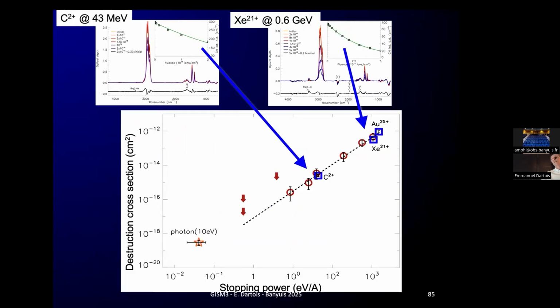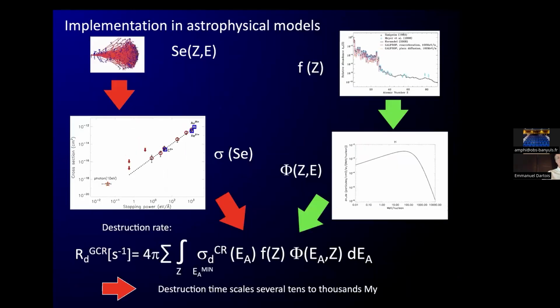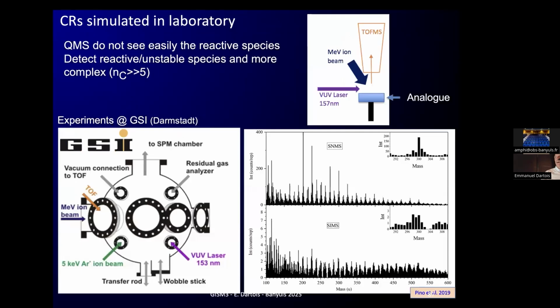You can see the destruction timescales, which is what we have in the hands-on, that we need to find the factor. And you can estimate the destruction rates, which are important to know if what you are seeing should be there or shouldn't be there, or do you need to reproduce these dust grains regularly, or are they resilient to the exposition of cosmic rays? And in some cases, if you're starting with AIB analogs, soot analogs, and you irradiate them with high energy ion beams mimicking cosmic rays, you can in fact eject species with a very high mass in the gas phase again. So the top-down chemistry can be active.